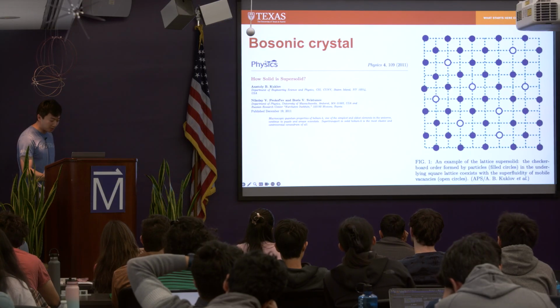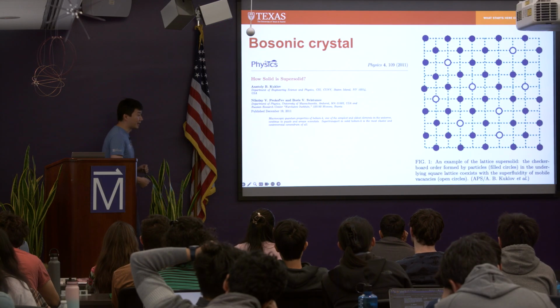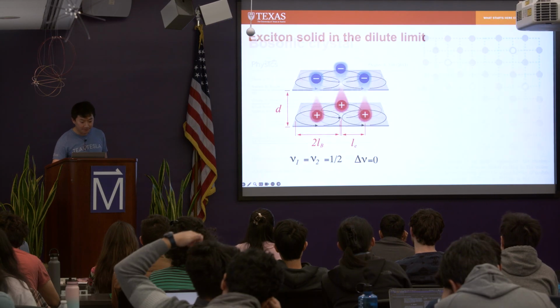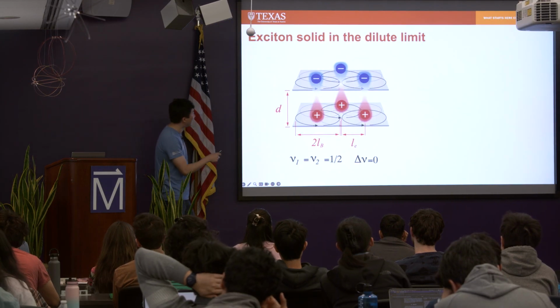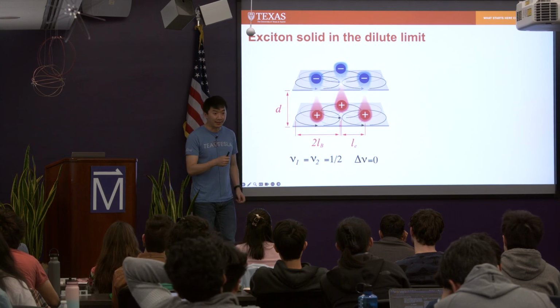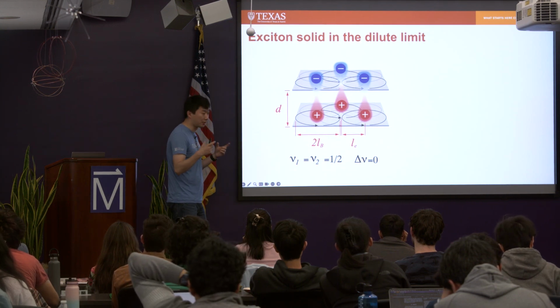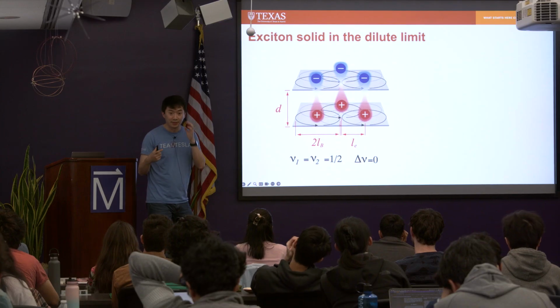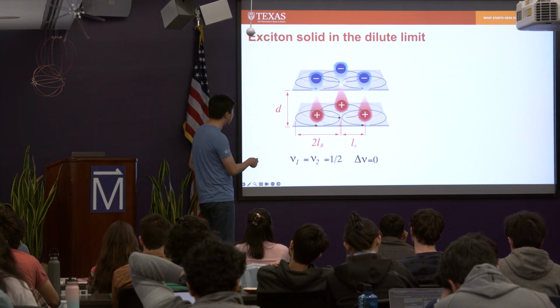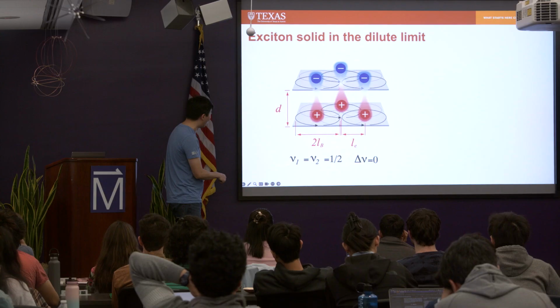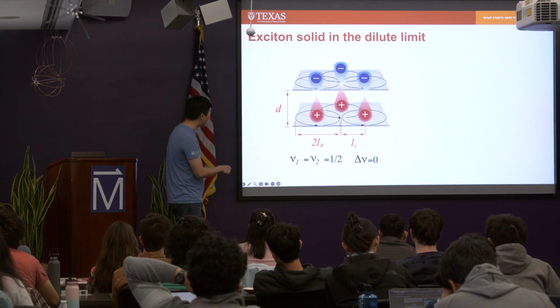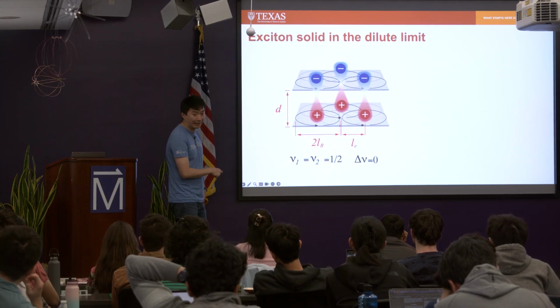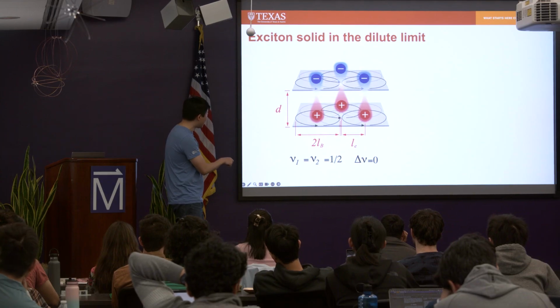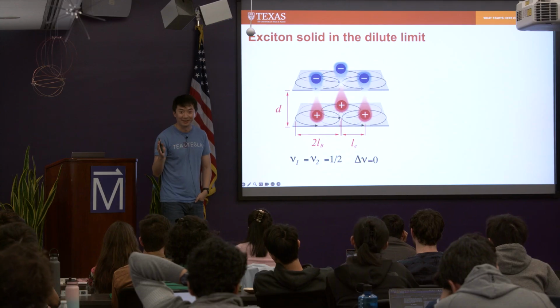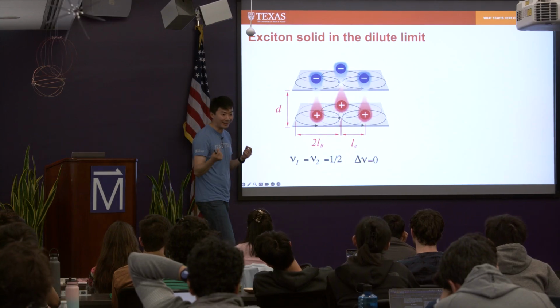And a lot of the proposals that I just mentioned that argue that excitons should form a solid argue that you need to go into the dilute limit, meaning that the separation between excitons should become much larger than the radius of the exciton itself, right? And that kind of outlines the issue. If we put a quantum Hall bilayer at 1/2 filling in both layers, right, the size of the exciton is defined by the magnetic length, right? And in this case, the separation between the excitons is also defined by magnetic length because you're at 1/2 filling, right? The separation is roughly 2 magnetic lengths.